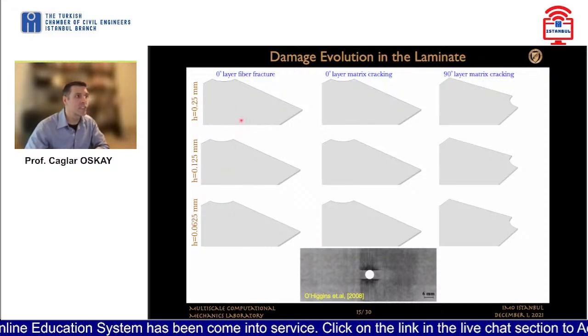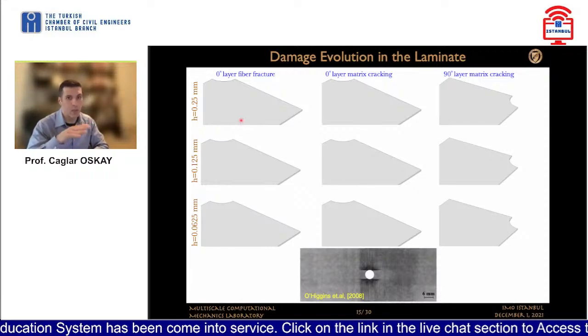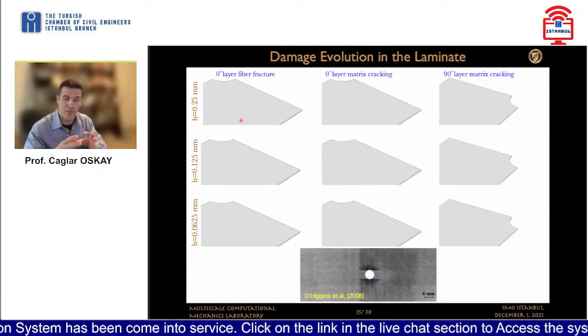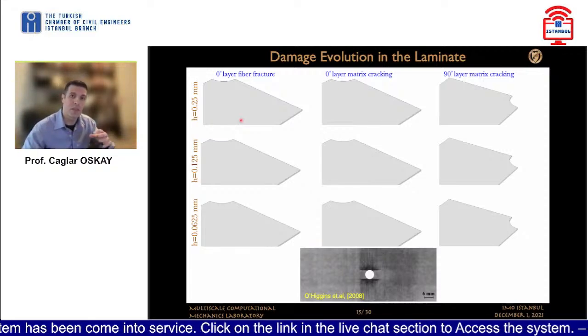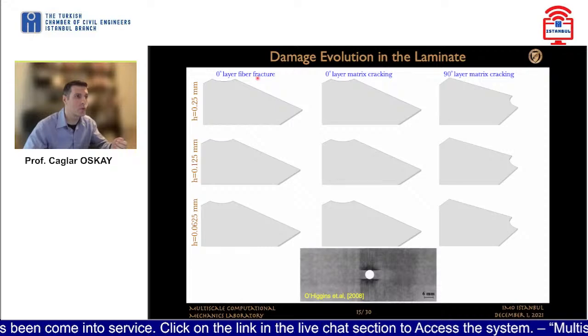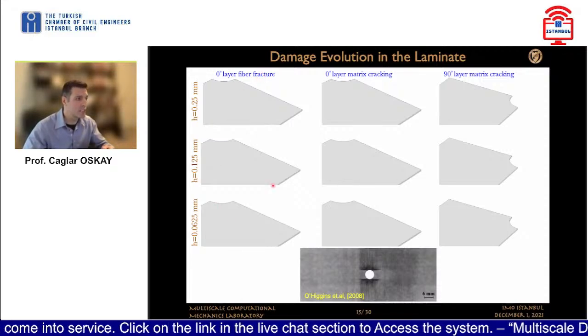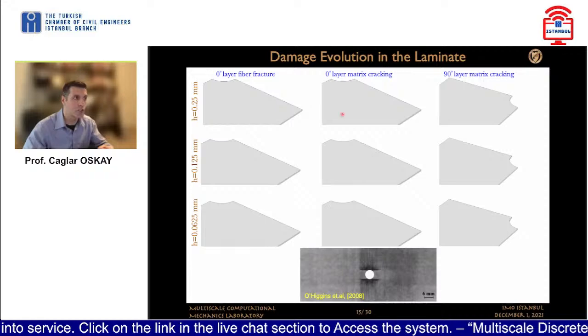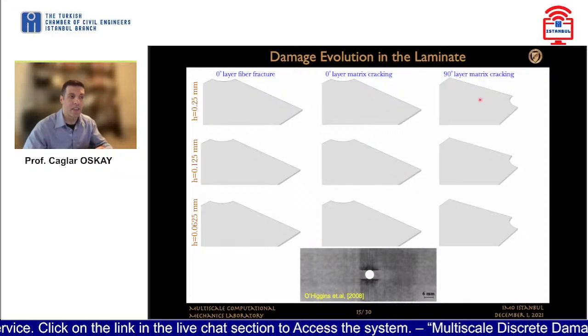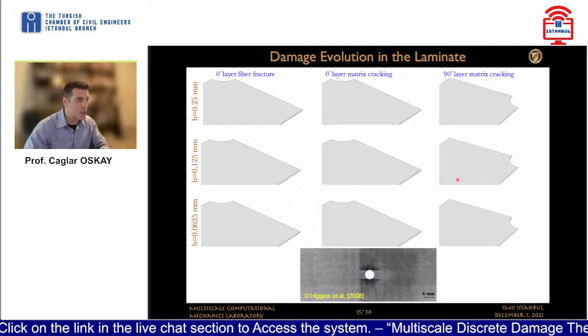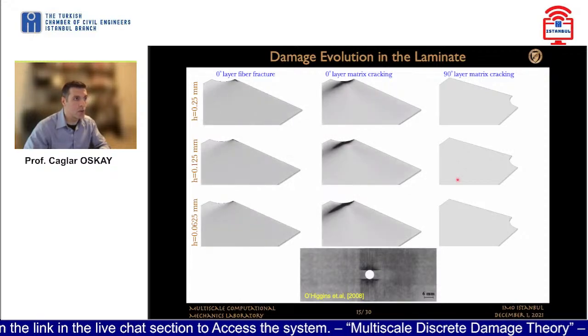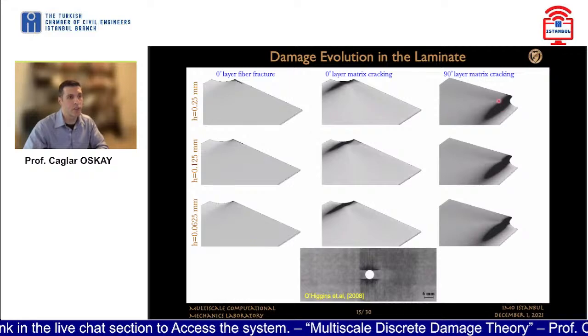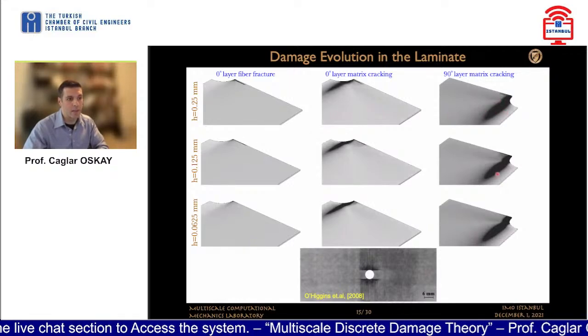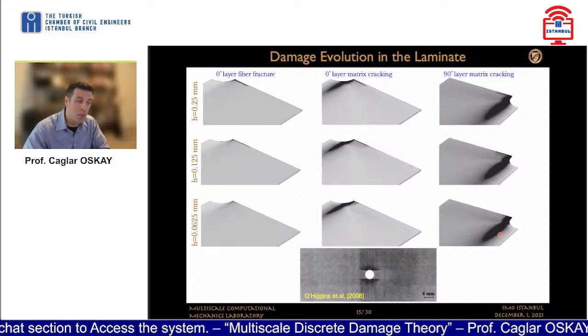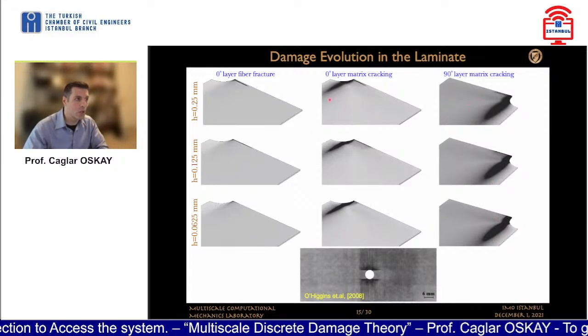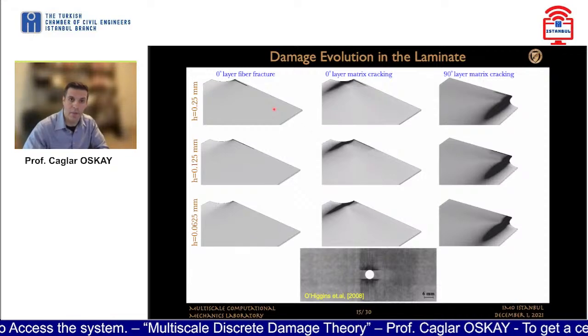The first is the 0-layer fiber fracture. We are modeling multiple different fracture failure mechanisms using the MDDT approach within the same simulation. But in this case, we're plotting the 0-layer fiber fractures, 0-layer matrix cracks, and the 90-layer matrix cracks. If we just look at the simulations and the overall behavior, as you can see, the behavior is essentially indistinguishable for the three different meshes in all the different kinds of failure behaviors.